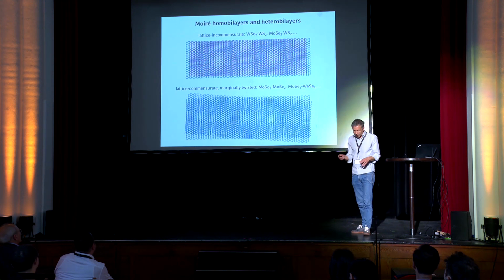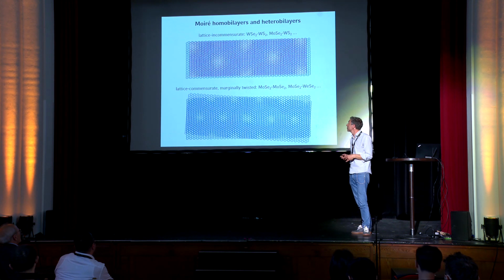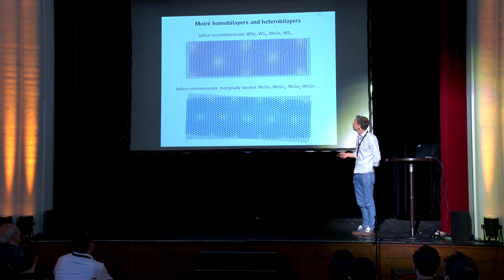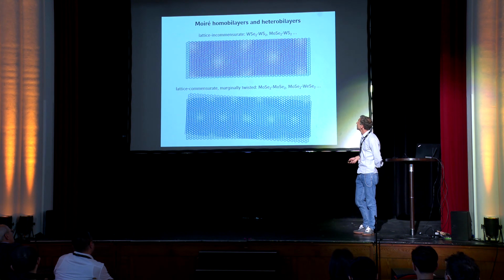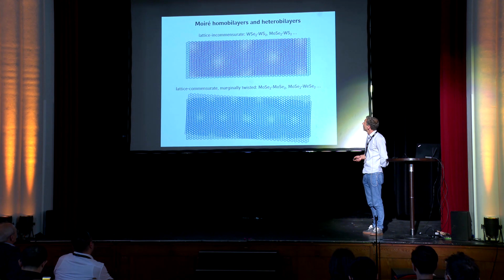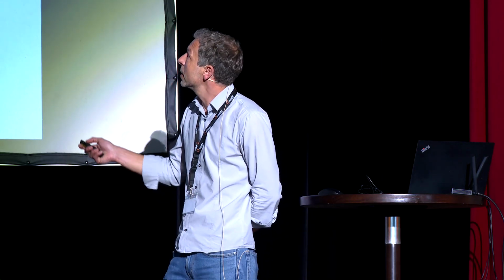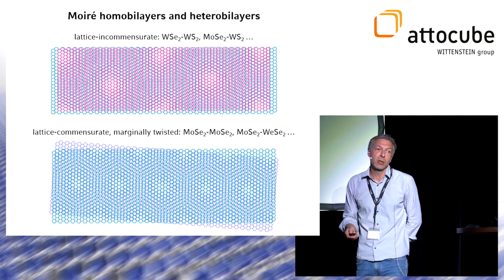So to begin with, I would like to point out that there are actually two rather distinct limits of such moiré heterostructures when it comes to transition metal dichalcogenides. So there are lattice incommensurate heterobilayer systems where you see that the transition metal is the same, yet the chalcogens are different. The lattice constants are different, of the order of a few %, and this is why such moiré lattices emerge without any twist, right? So already at perfect alignment, because of lattice mismatch, we would have this two-dimensional modulation in the interference pattern.